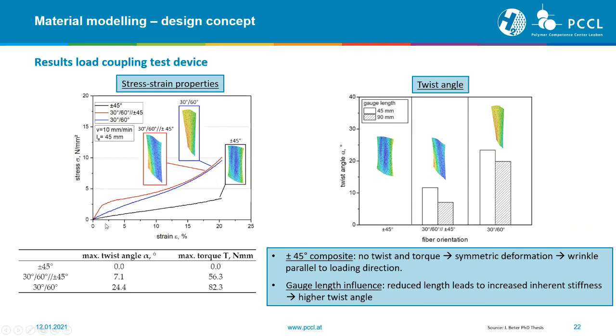What you can see very clearly is that we've monitored the stress depending on the strain for plus minus 45, 30-60, and 30-60 plus minus 45. All of these are two-layer buildups, which means 2 layers of plus minus 45, 2 layers of 30-60, and here 1 layer 30-60, 1 layer plus minus 45. You see here clearly the different material behavior. Additionally, we've also implemented a study with different clamping distances or gauge lengths. And you also see here that for the twist angle for plus minus 45, we received nearly nothing, whereas for 30-60, we received a twist angle of up to 25 degrees.